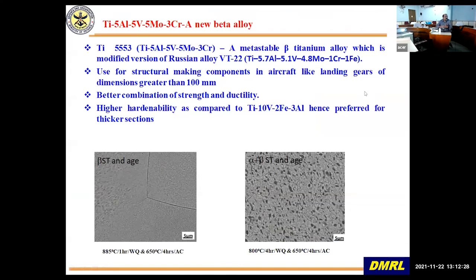The other alloy that we are working on is 5553. This has got higher hardenability as compared to 10-3. This is required for higher section size thickness for making bigger components. So we had done a lot of lab scale studies, both in beta treated condition and alpha plus beta deformed, solution treated and aged condition.